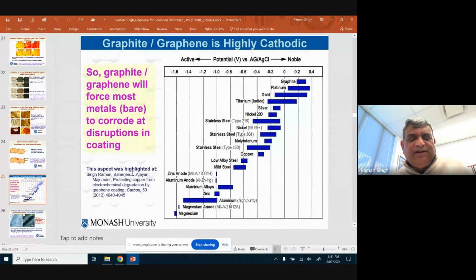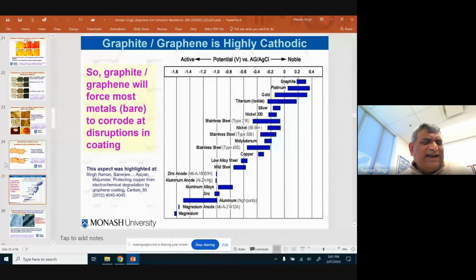In our paper just a year before, we had said that you must have a continuous layer of graphene. If you don't have a continuous layer, at the locations of disruption the corrosion is bound to be high, simply because of this simple electrochemical fact that graphite is highly cathodic. If you attach graphite to any engineering material, it will force that material to corrode at a higher rate, because graphite will be acting cathodic, and the other metal that you're attaching it to will act anodic, and corrosion will be accelerated. That's exactly what was happening in their case.